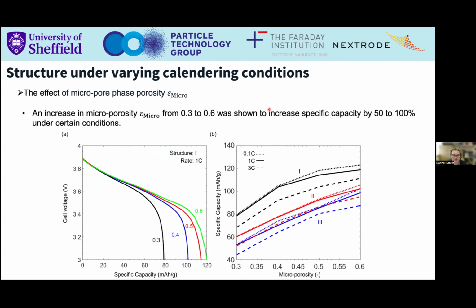So we increased our microporosity, and what we found was that when we increase our microporosity, we massively increase our specific capacity under certain conditions. And so this was a really important finding. What this means is that if in manufacturing we can change our microporosity inside the electrode, we can start to really control the electrode performance, or at least influence it substantially, without putting more active particles in there.